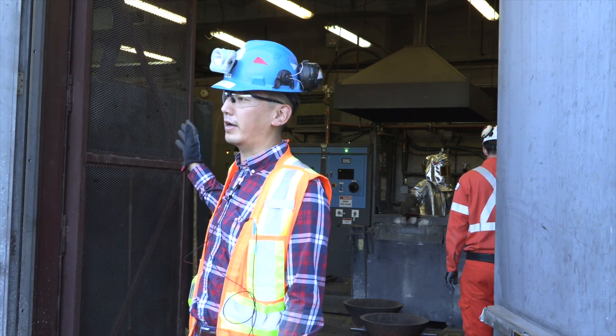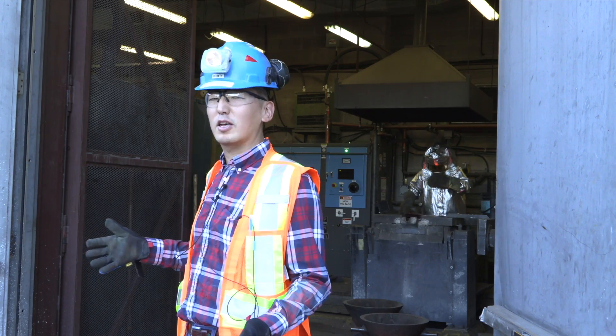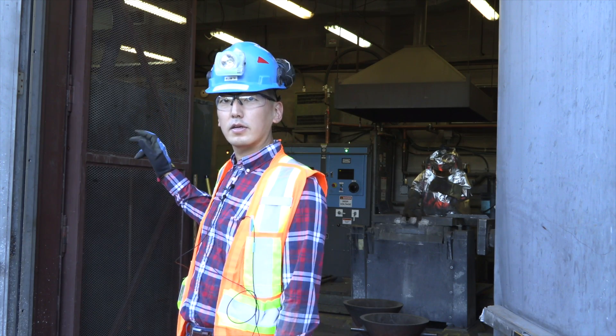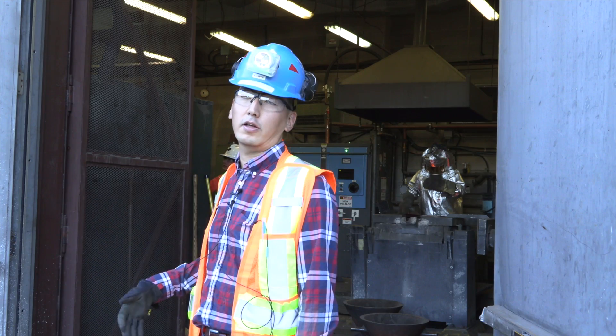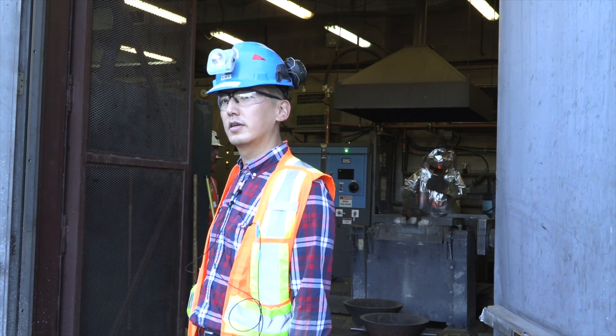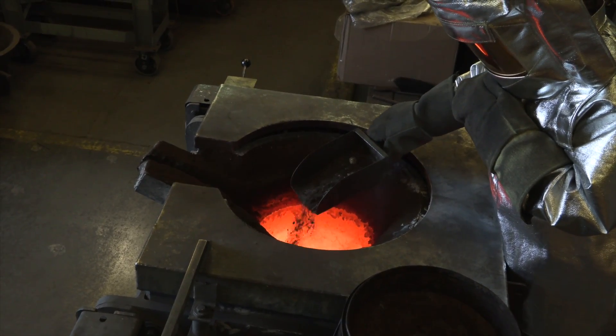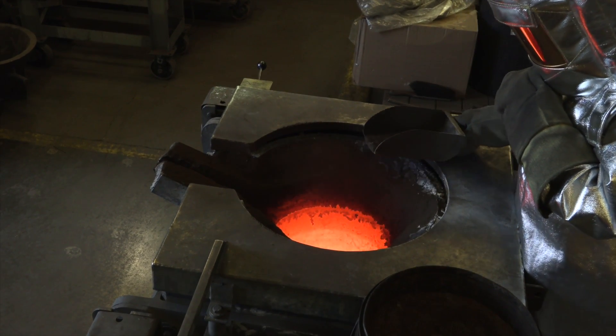William Ty is the engineer in charge of the mill. Let's hear what he has to say about how they get the gold out of the water. By the time the material comes into the refinery, it's a solution — we call it loaded solution. It's typically between 6 to 13 ounces per ton gold. It goes through two electrowinning cells. The gold plates onto the cathodes. That material is collected weekly — we drain out the electrowinning cells every week. The concentrate goes through the filter press where we dewater it, remove the moisture. It goes into an oven overnight. We get a dry concentrate and that dry concentrate is the material that goes into the furnace.